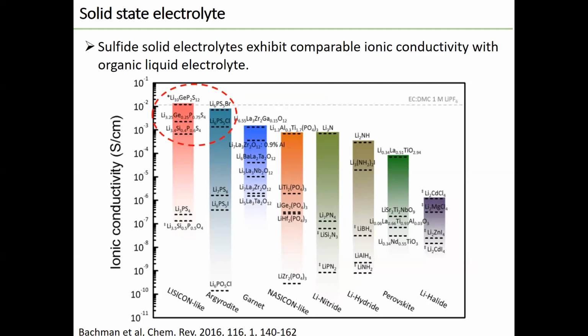Among these candidates, sulfide electrolyte is one of the most popular ceramic electrolytes, which has comparable ionic conductivity with liquid electrolyte. This advantage renders sulfide electrolyte based solid-state batteries working at room temperature without sacrificing performance. In comparison, other electrolytes like the oxide and the polymer still need external heating to achieve a considerable performance.